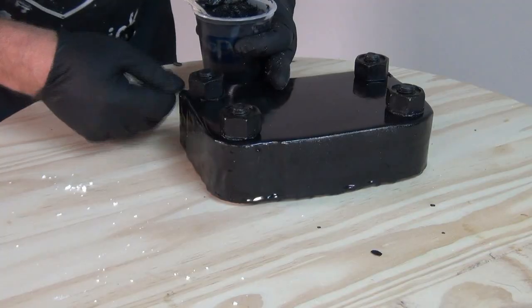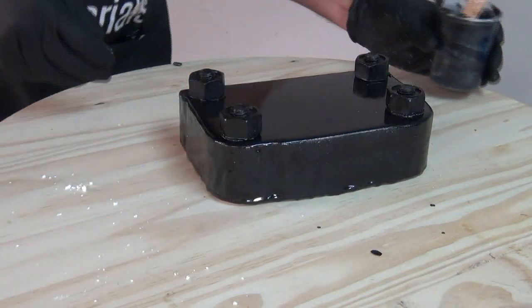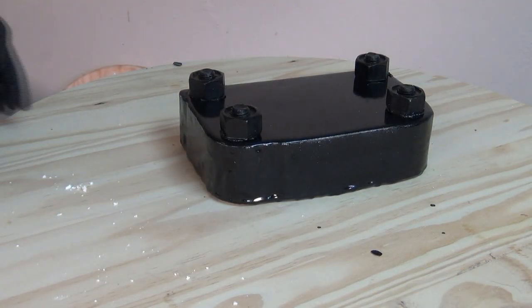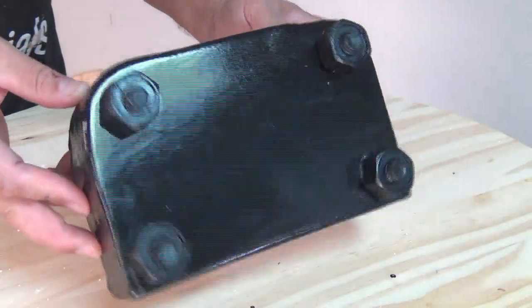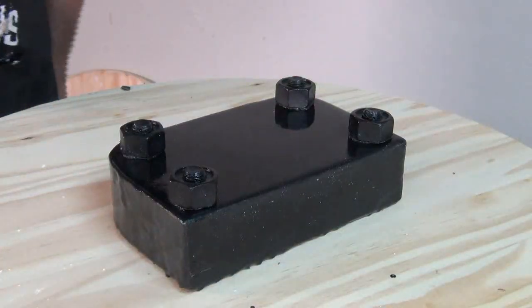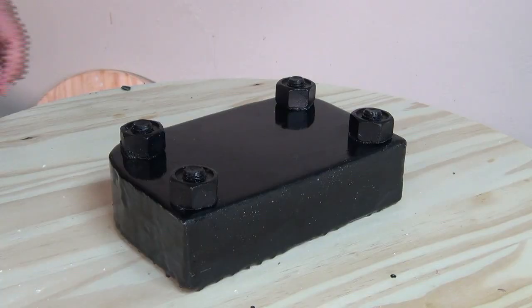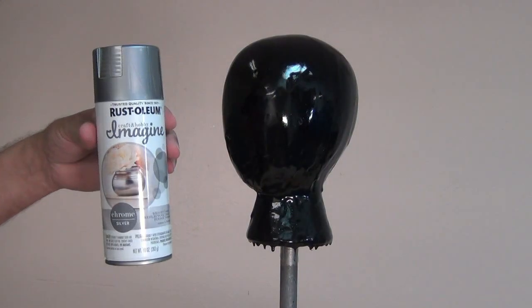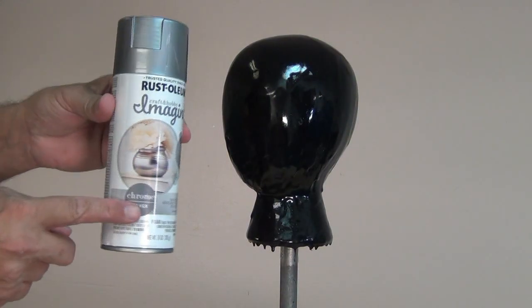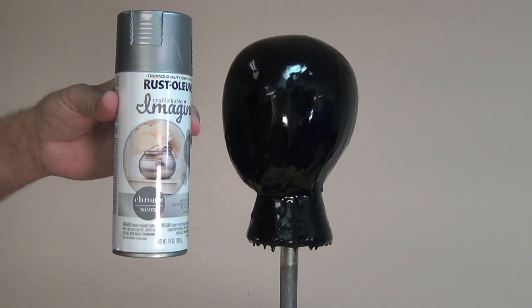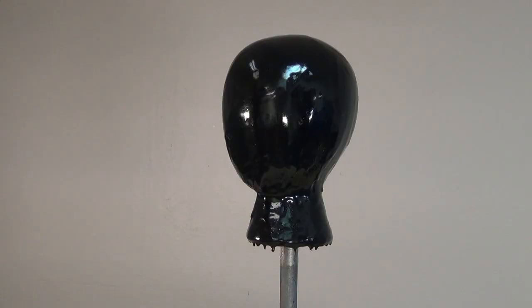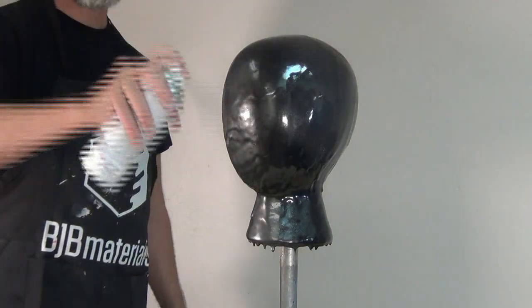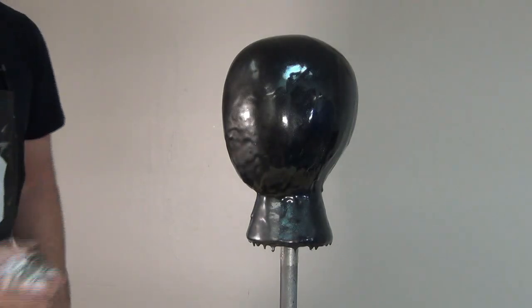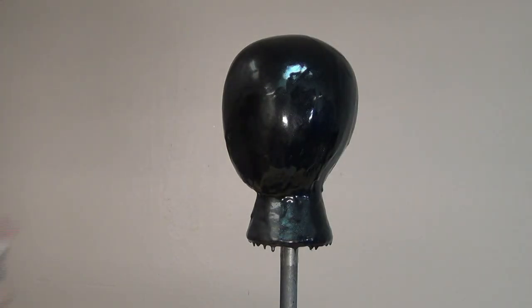So in a more involved tutorial, I might actually rough up those areas and sand them a little bit before I stick down some bolts like that. But this actually got a really good bond, and everything stayed really well put once I stuck it all together. And the impact resistance was really good. And this was the part that actually really surprised me, because again, in my haste and my desire to just run this through all its paces, I didn't even primer this part, and just applied the cheapest chrome or silver spray paint that I could find over the top.